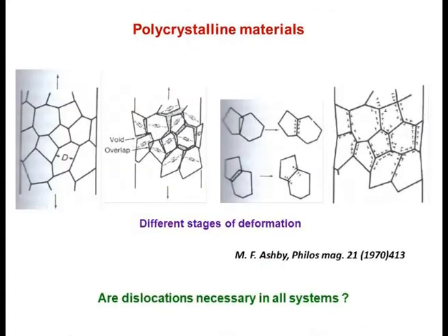If you take a polycrystalline material, then essentially we'll have grains. When the deformation is being given, the grains should not come apart. Because of that, there are going to be constraints, but it has to deform uniformly. That will lead to a lot of dislocation interactions, and we'll finally be left with a lot of statistically stored dislocations, then geometrically necessary dislocations. All these things are going to be present in the material.